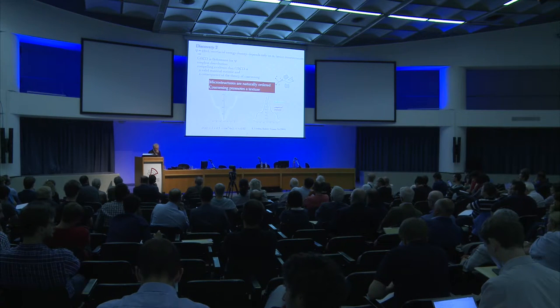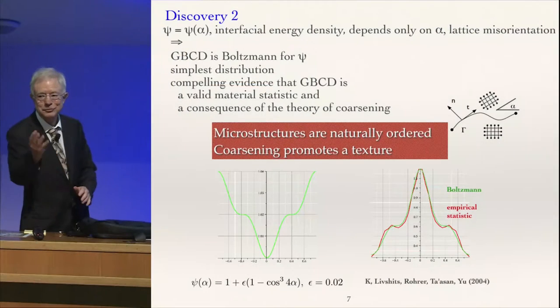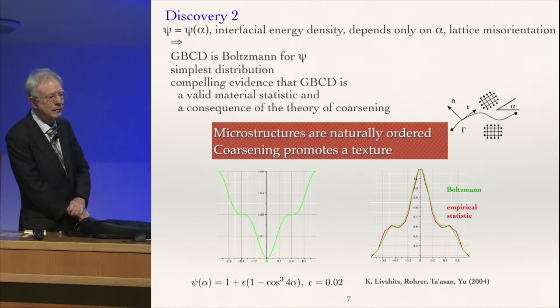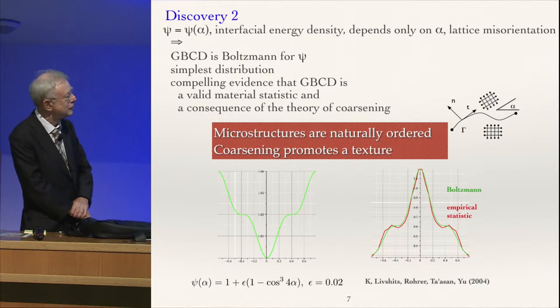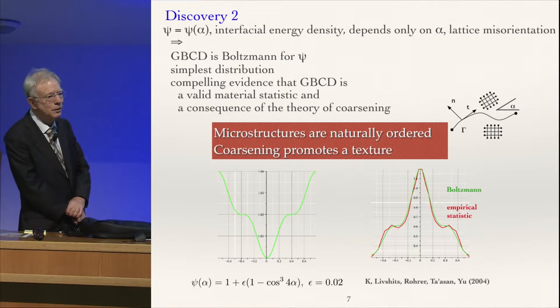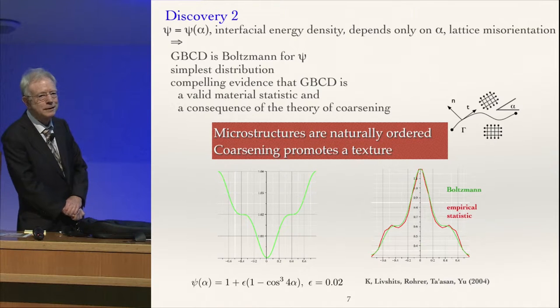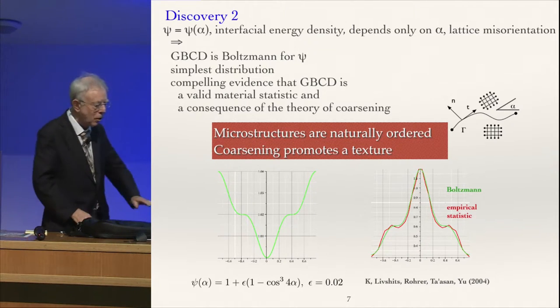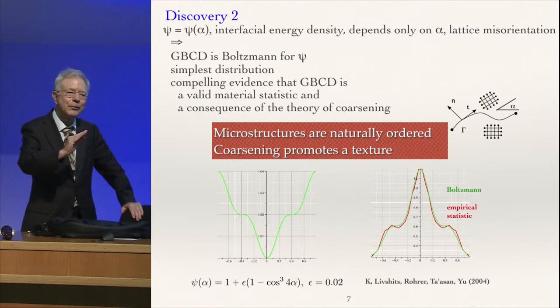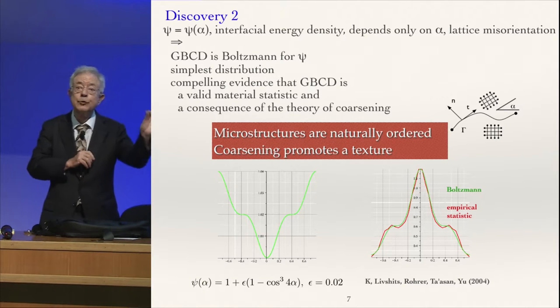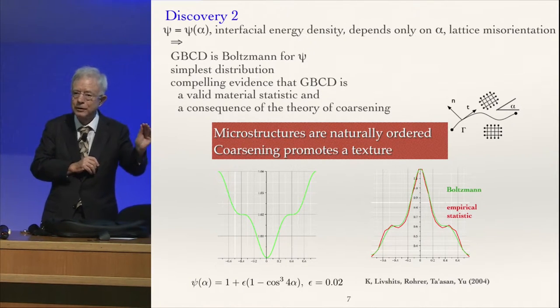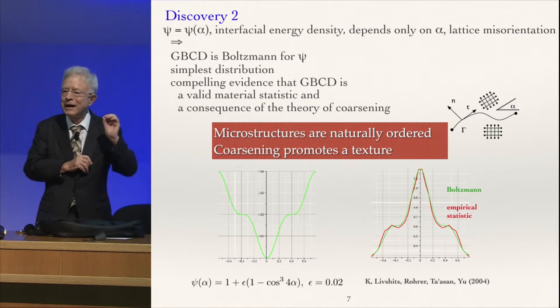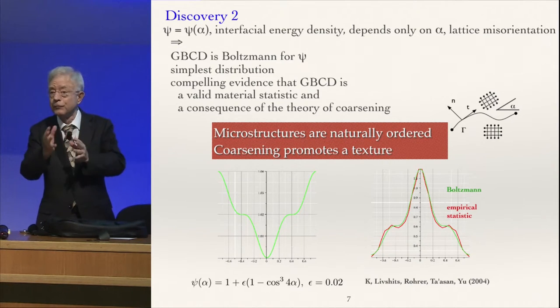So it's very easy to think of possible things which are statistics, like the number of people in the room with a given name, but which you have no reason to believe are statistics. One example is grain orientations. Not the grain boundary orientations, but the grain orientations are frequently collected and resolved as statistics. But as you will see, because we are able to make a good theory for the grain boundary character distribution, there can be no theory for the grain orientations per se. There has to be extra processing to deliver the grain orientations, because it's the boundaries which are making the configuration.